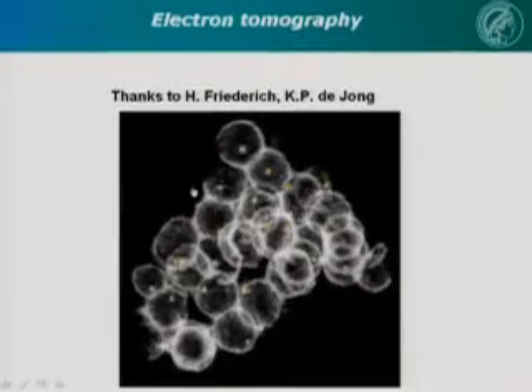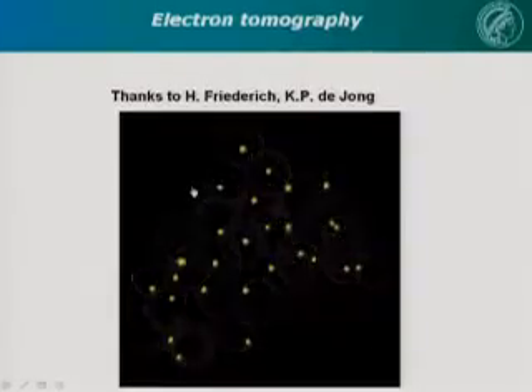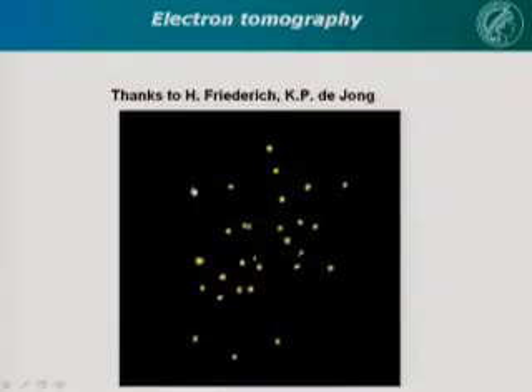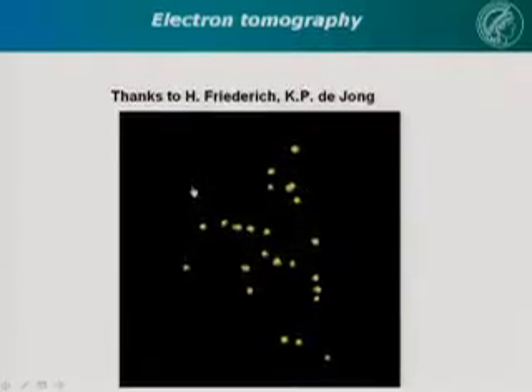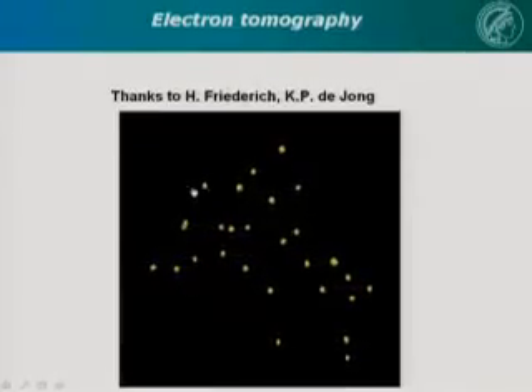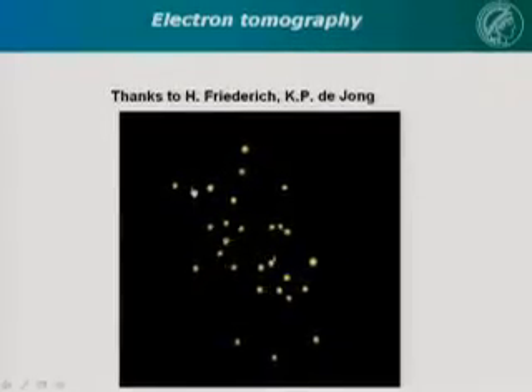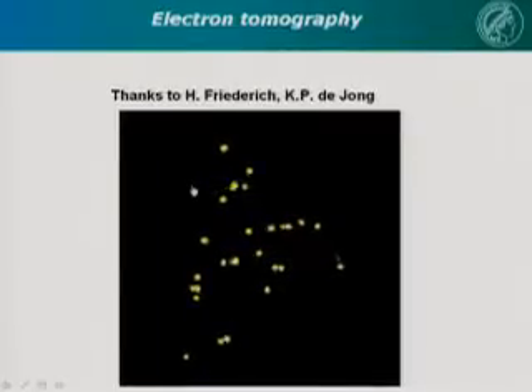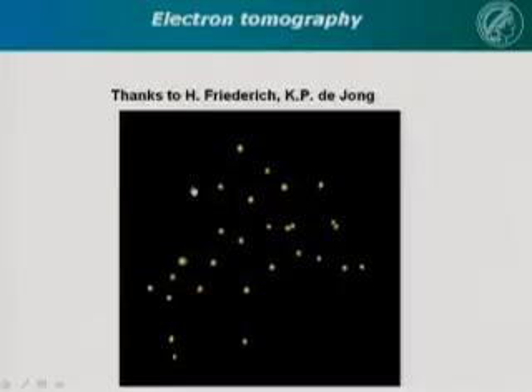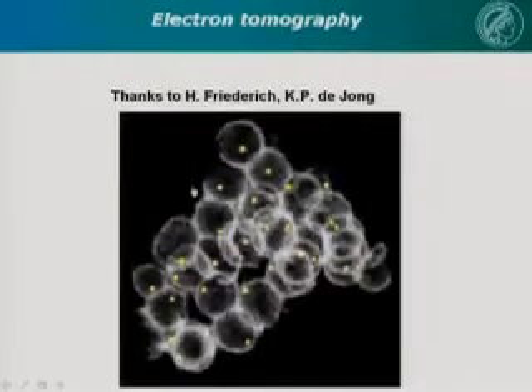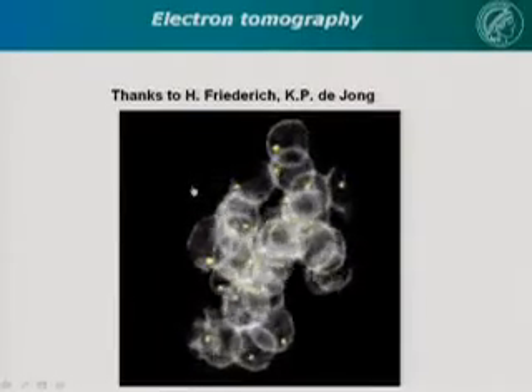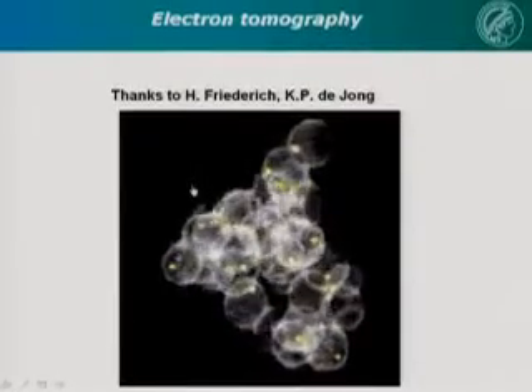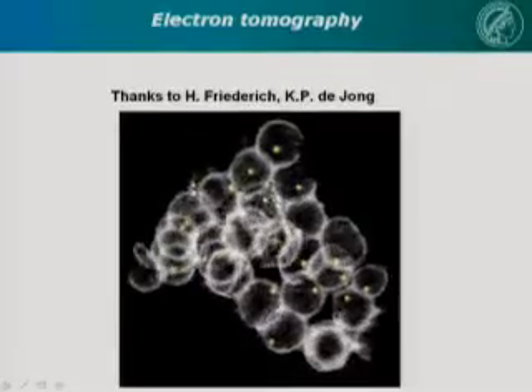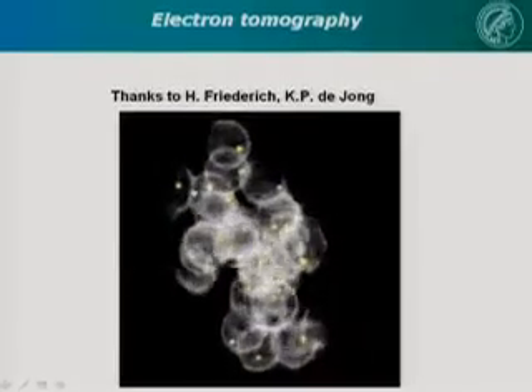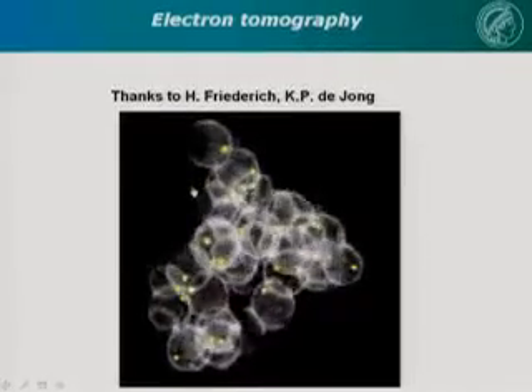The next one you see, they only took the gold particles and removed the shells, and you see all the gold particles basically have the same size, and they're all isolated. They are not two hanging together. And now they put everything back together, and you can, let's say, focus on this particle. You see this is alone in this particular shell. This one here is alone in this particular shell, and this can be expected from the synthetic protocol.